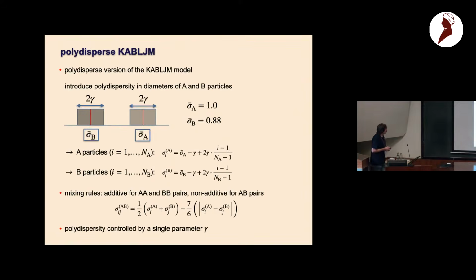Now one can make this Kob-Andersen mixture polydisperse, and we do it in the following manner: we use a polydispersity for the B particles and the A particles. This can be described by assigning to each particle in a uniform and deterministic manner a diameter via these rules, and there's only one parameter with which one can control the polydispersity for both A and B particles. Then we use the same mixing rule as in the original model.